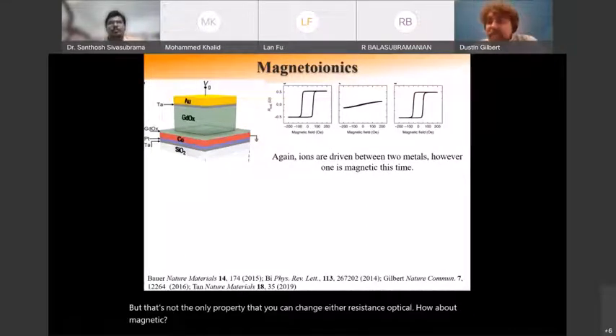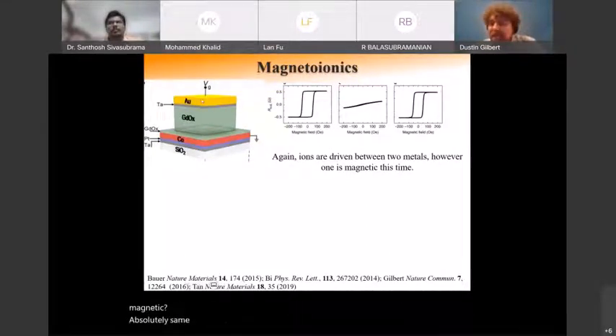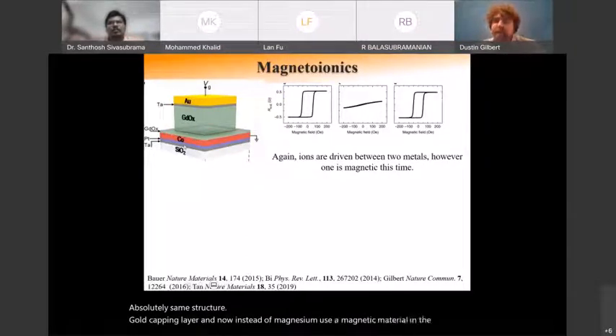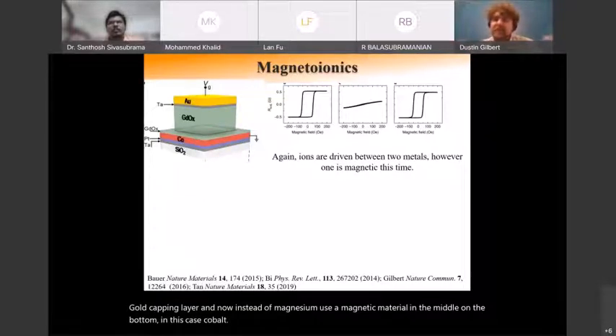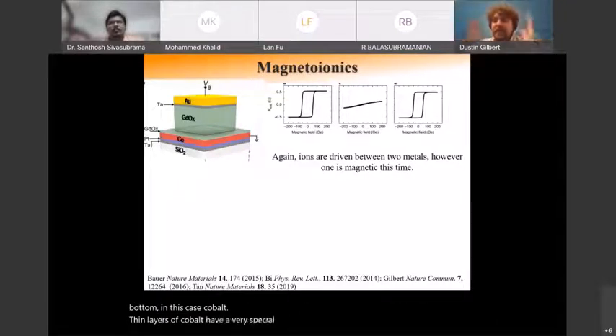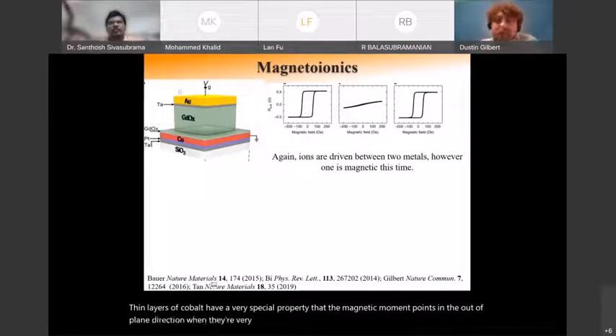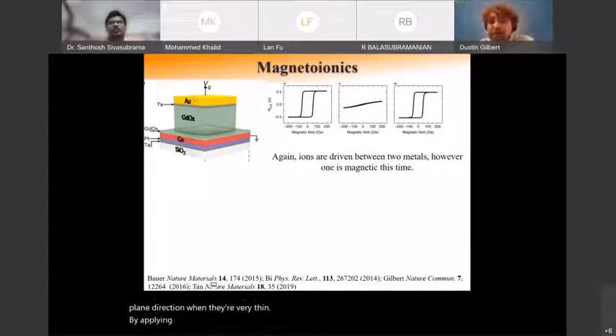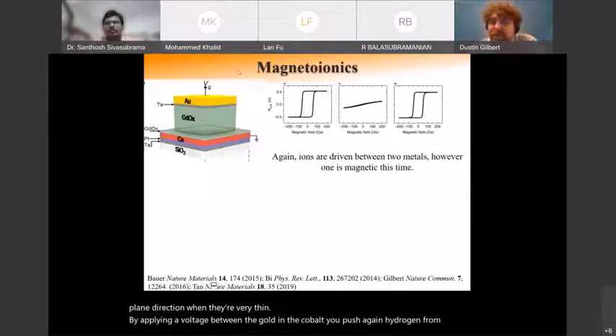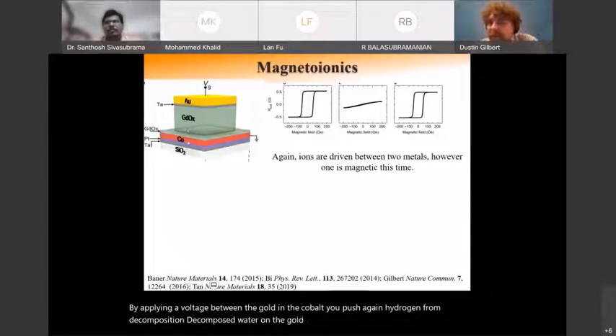Absolutely, same structure. Gold capping layer, and now instead of magnesium, you use a magnetic material on the bottom, in this case, cobalt. Thin layers of cobalt have a very special property that the magnetic moment points in the out of plane direction when they're very thin. By applying a voltage between the gold and the cobalt, you push again hydrogen from decomposed water on the gold surface through the gadolinium oxide layer and into the cobalt.